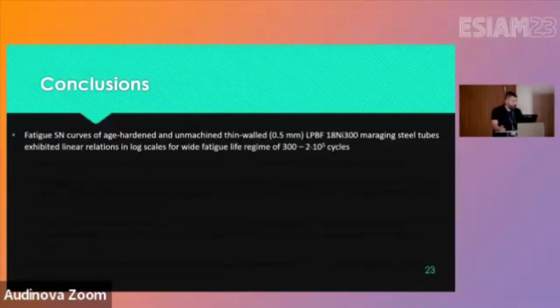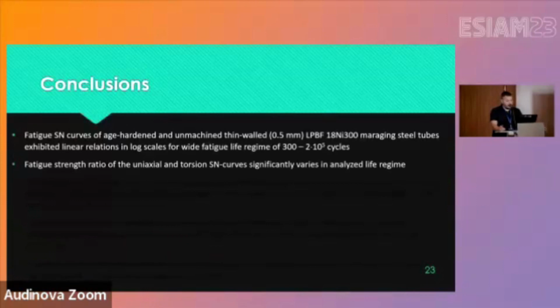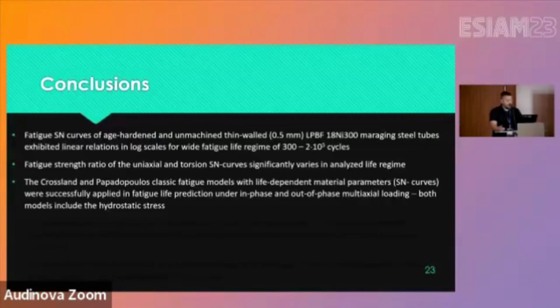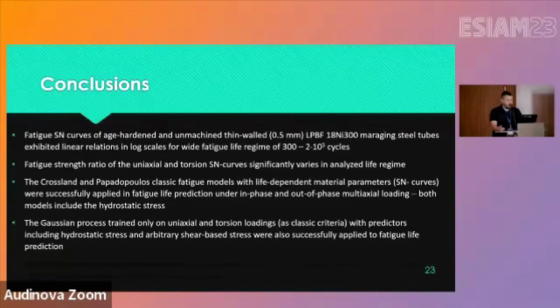It's not so great. And there's the conclusion only. To summarize, the fatigue S-N curves of heat-treated and unmachined thin-walled maraging steel tubes exhibited linear relations in log scales for a wide fatigue range. Fatigue strength ratio significantly varies in the analyzed regime. Crossland and Papadopoulos classic fatigue models with life-dependent material parameters were successfully applied in fatigue life prediction for in-phase and out-of-phase multi-axial loading, and they both include hydrostatic stress. That was their main reason.